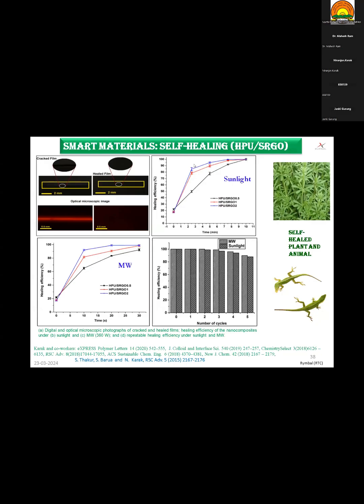The system can also be used to self-heal. We know that some special animals or plants can heal themselves, whereas a material cannot, because it is a non-living thing. That is the concept. However, in recent studies and in our research also, we have seen that even a material can heal its damaged surface by itself by application of some stimulus like microwave, sunlight, heat energy, or solvent. And here you can see from these images that when damaged surfaces are exposed to microwave or sunlight, they can heal with almost the same efficiency, 90 to 95%, and it can be done repeatedly without significant loss of efficiency.